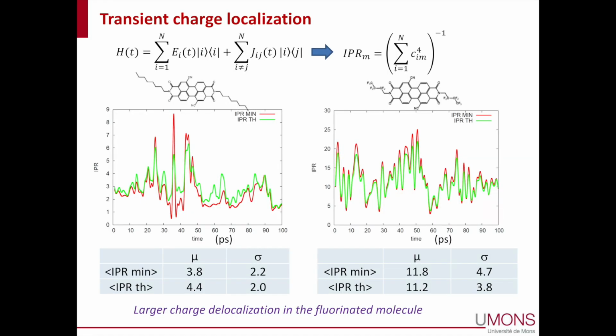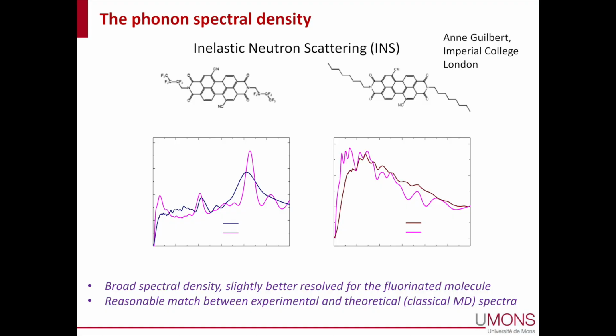So now you can ask yourself, I mean, there's the dimensionality issue, but also we know, and Henning has described this in great detail, that those phonon modes, motion of the molecules with respect to one another, will ruin the transport properties. So we can ask ourselves, what are those killer modes? For this, first you need to get a handle on the description of all the phonons in the system, and you can do this by simulation of the inelastic neutron scattering shown here for the 2 molecules, and those compare reasonably well to experimental data, considering the fact that these are simple classical force fields. So the comparison is quite good.